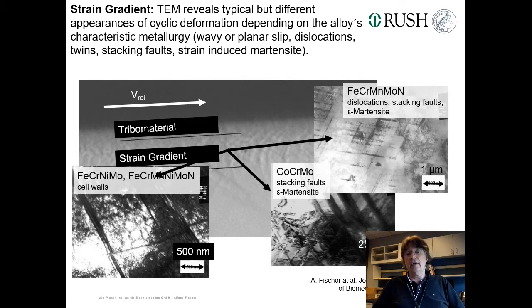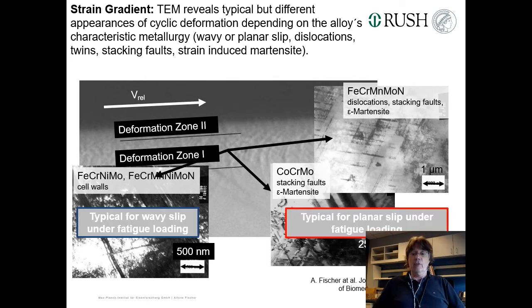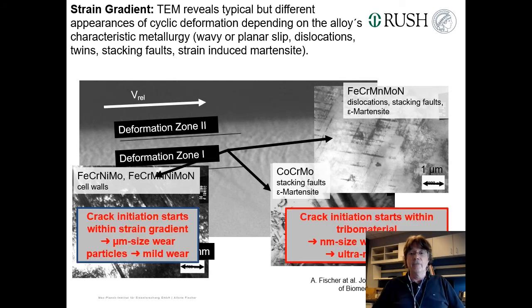While as long as the lattice defects stay on the discrete sliding planes, they also block each other, but they remain mobile. This is typical for wavy sliding materials under fatigue loading, while this is typical for planar sliding materials under fatigue loading. So, meaning here, the crack initiation and propagation in order to generate a wear particle, one of the nanometer-sized wear particles, must have started here. While if you get micrometer-sized wear particles, crack initiation and propagation must have started down here.